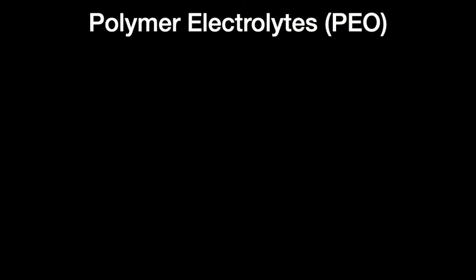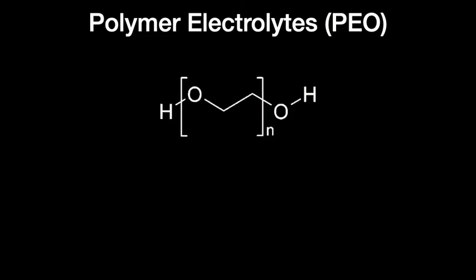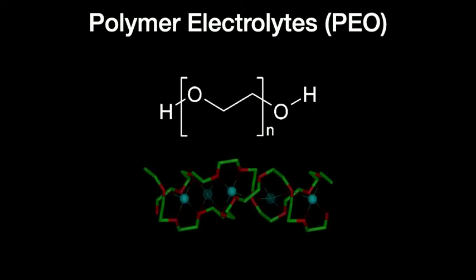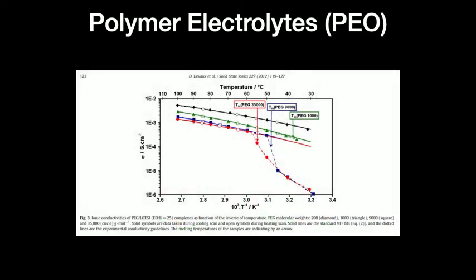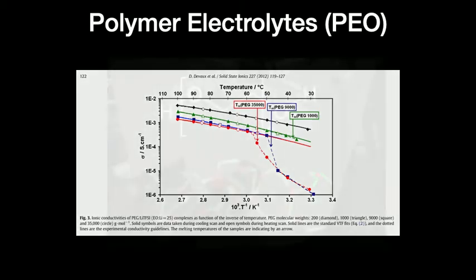Polymer electrolytes are mostly PEO type electrolytes. You can see the ether oxygen linkages in these polymers, and they solvate lithium ions, allowing lithium to move through the polymer in a kind of segmental motion. The problem, of course, is that these are conductive, but again, they fall off pretty rapidly as you approach room temperature, so they're not appropriate for room temperature batteries. These have to be higher temperature batteries.